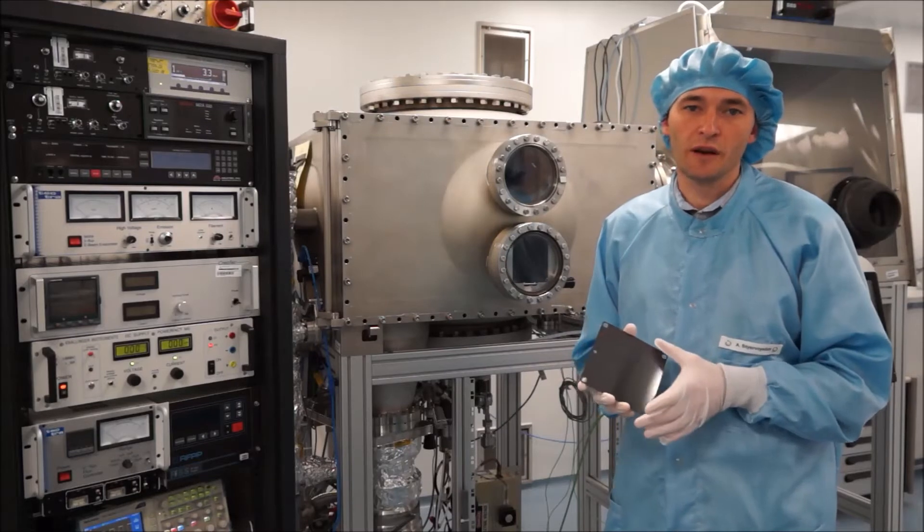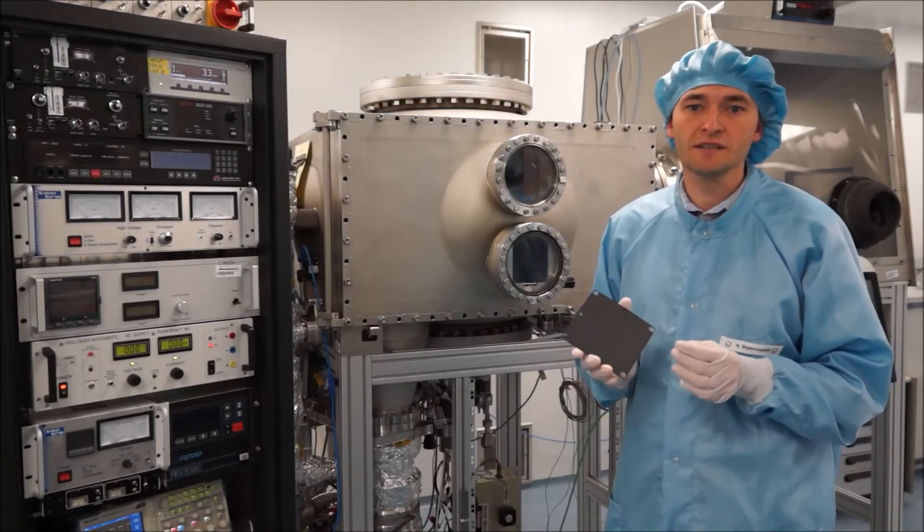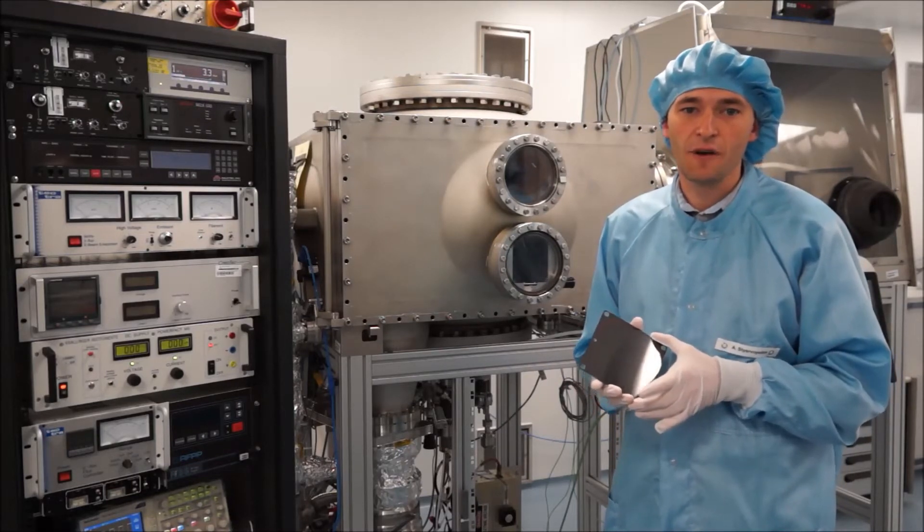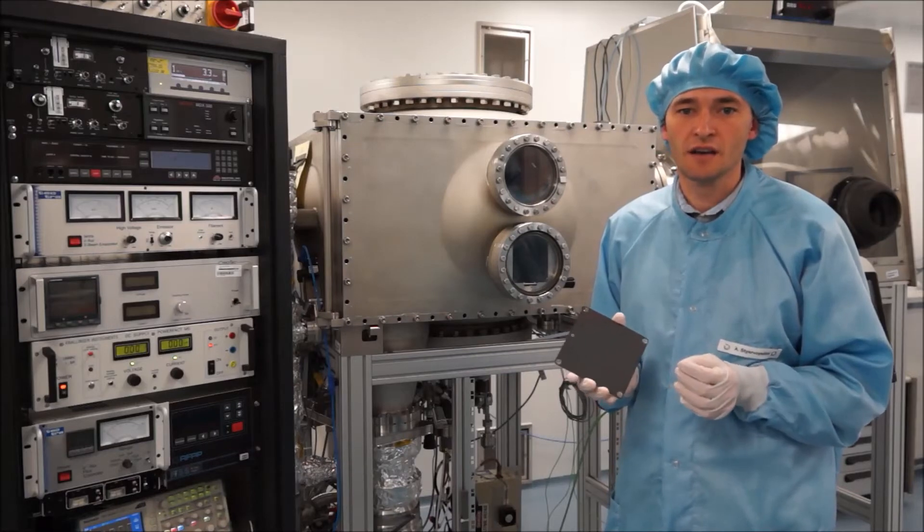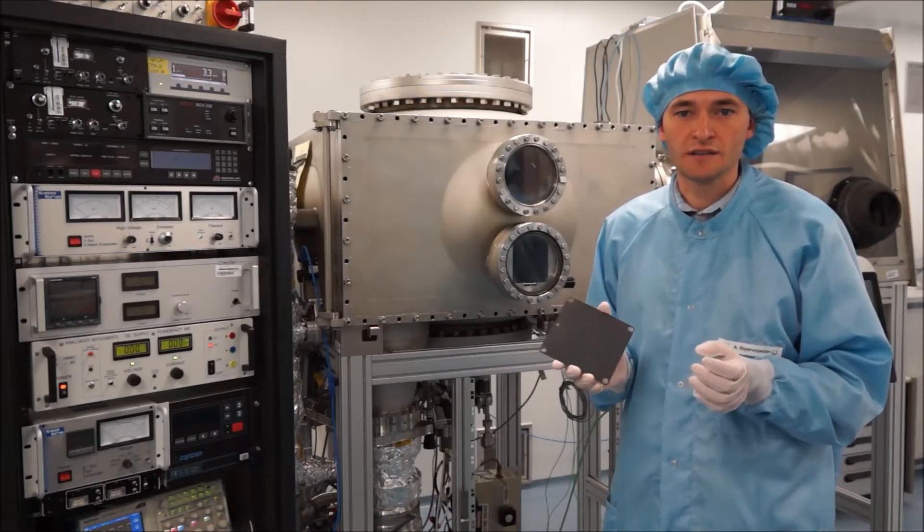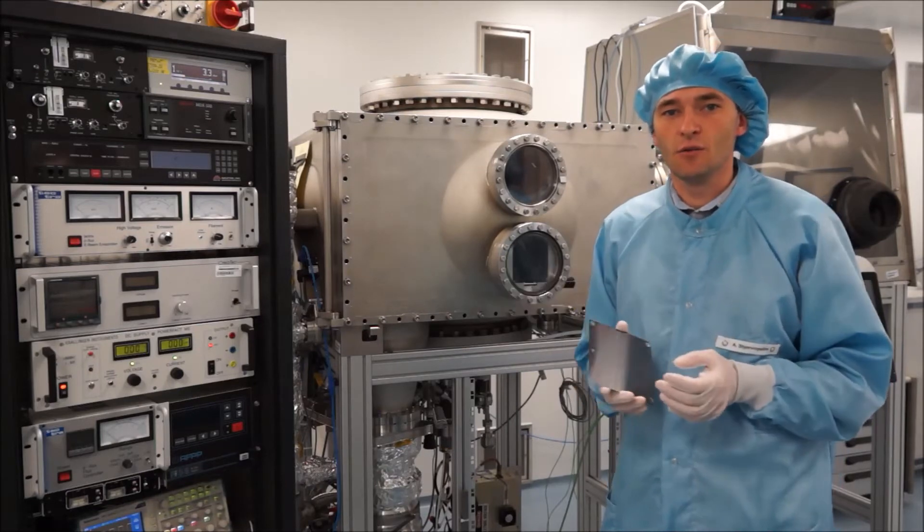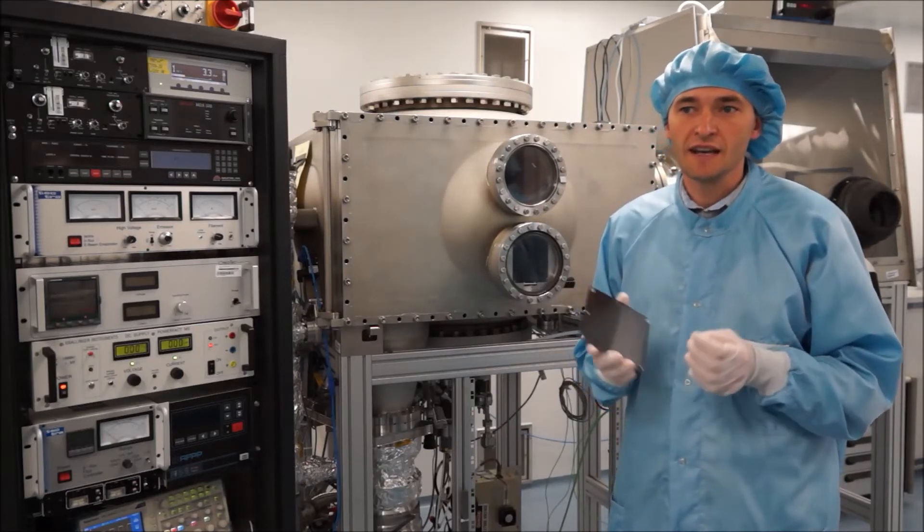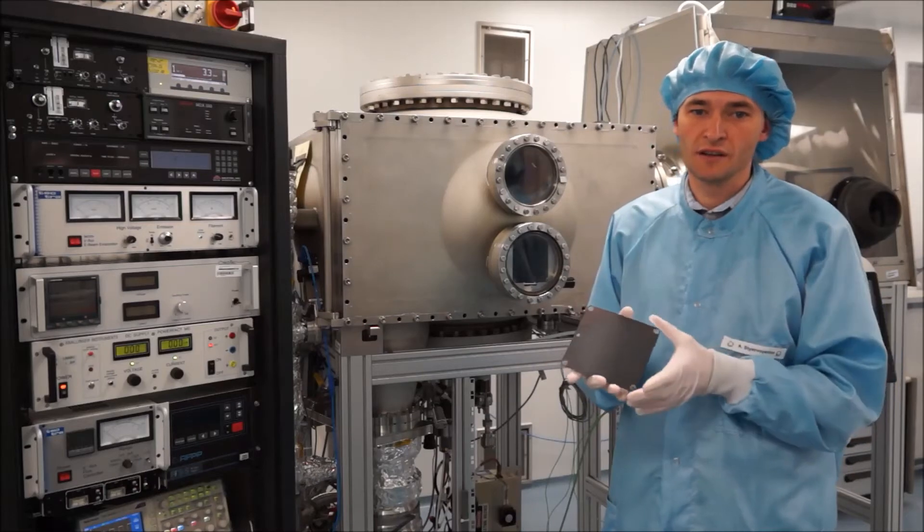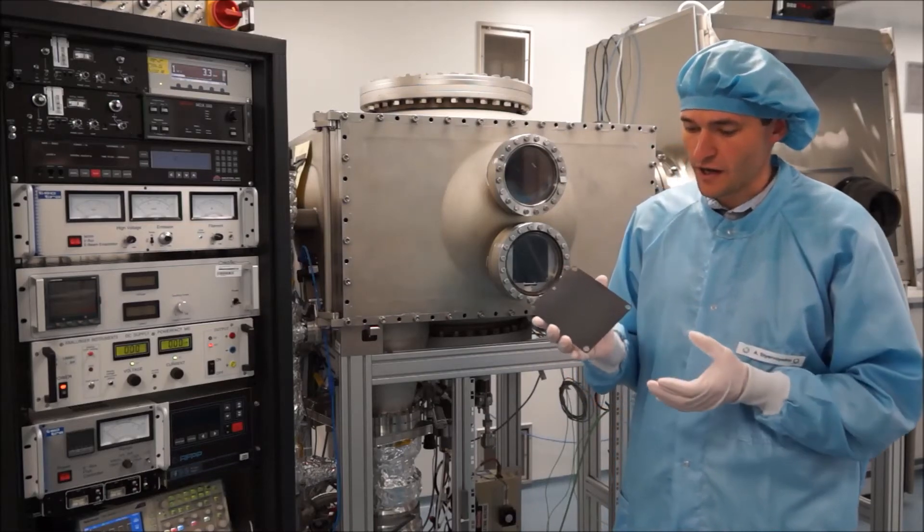Compared to conventional magnetron sputtering, HIPIMS generates dense plasma with high fraction of target metal ions, in our case boron ions, and thus provides improved adhesion and density of the coatings. As a result, we got boron-10 carbide layers of very high quality.